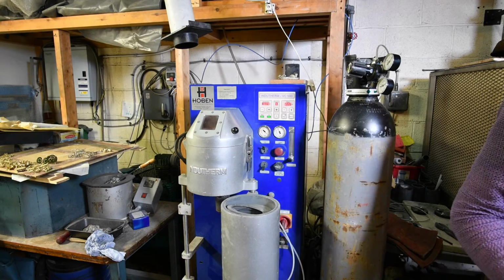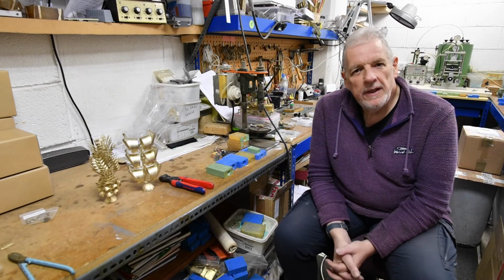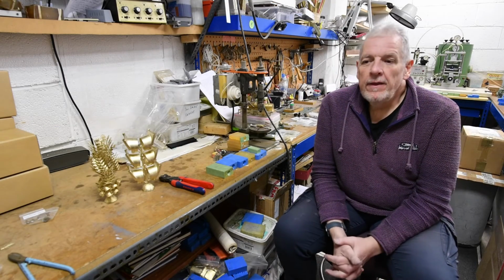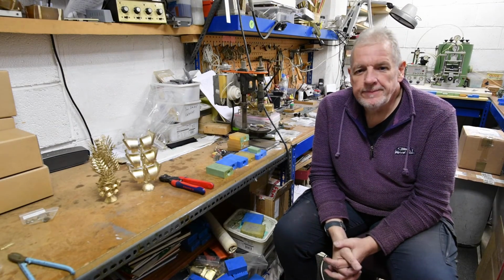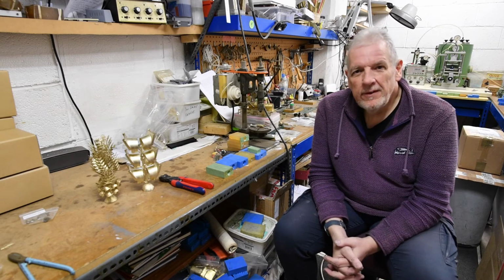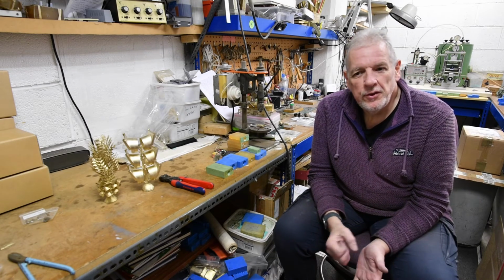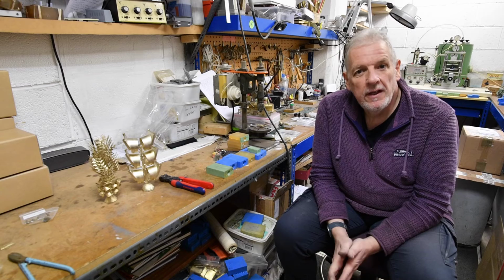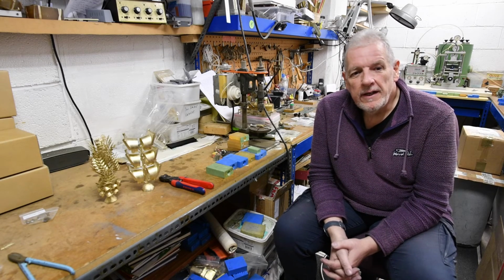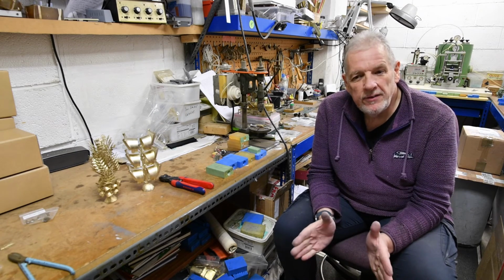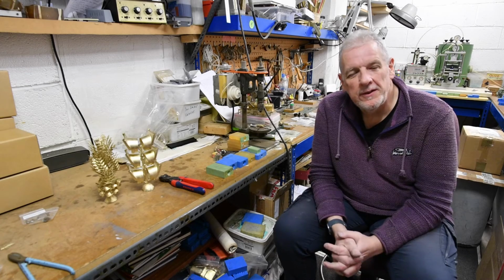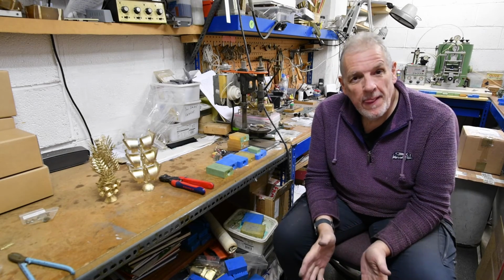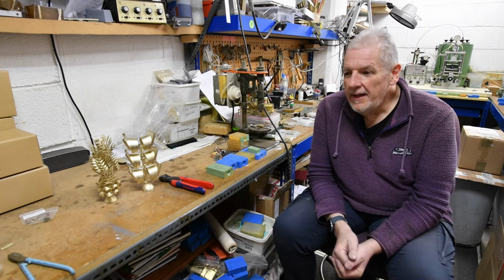to cool. Once the flasks have been allowed to cool, they then go through into a blasting off cabinet, where a pressure washer is used to blast the plaster off the castings, and then they go through various different dips to clean the castings up, and then they're set to one side, usually in the open mouth of the kiln in my case, to dry, and then I bring them in here and I sit and I cut them off.